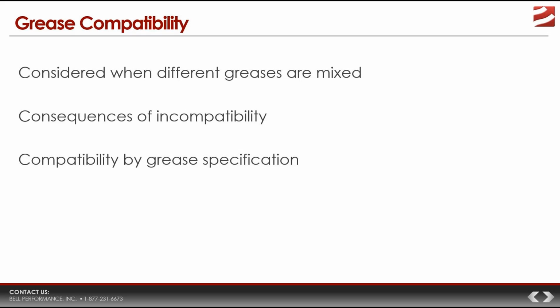At its heart, remember, grease is a heavy base oil, the lubricant, combined with some kind of soap thickener. The soap thickener traps the lubricant oil and makes it thick and stringy enough that it stays in place when put into an area with moving parts. When we use the term soap in this context, remember, we're not talking about the kind of soap you wash your hands with. We're talking about a class of compounds that result from reacting an acid and a base together. In making grease, they take that fatty acid, introduce a metal base or some other complexing agent, and react it with a base like sodium hydroxide to get the soap thickener used to manufacture grease.